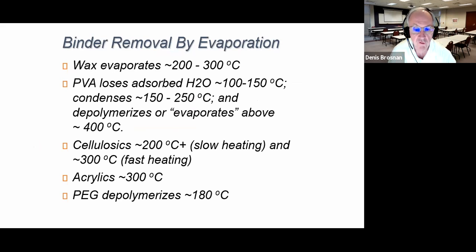If you are using organic binders, then of course, I was taught as a ceramic engineer that binders burn out, carbon oxidizes. Well, that's not always the case with some of these higher molecular weight substances that are used today. You can see that wax will evaporate at fairly low temperatures. Polyvinyl alcohol goes through a loss of some water and depolymerizes, breaks into molecular fragments and evaporates above about 400 degrees C. So you can see the same kind of information from cellulosics and polyethylene glycol used as a lubricant, and a lot of our products will depolymerize around 180 degrees C. Of course, it's always important to get these binders out before any sintering begins.